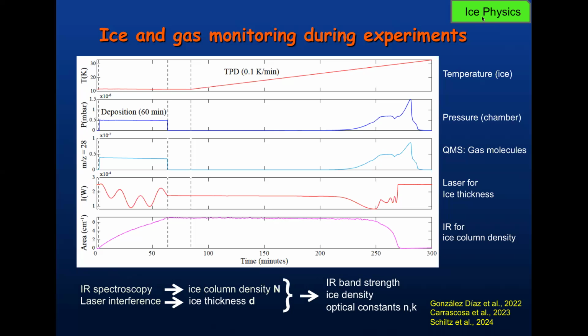We also measure the volumetric density of the ices and the optical constants, N and K, which are very important also for astronomy. N is the refractive index, K the absorption. With these you can produce spectra, and you can use different morphologies of the ice, a spherical grain or a more elongated one, so that you can reproduce more realistic spectra, okay? And even maybe convert these absorbance infrared spectra to reflectance, which is very useful for the ices in the solar system.